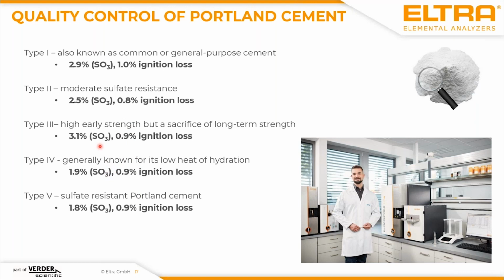the long-term strength of the cement decreases, which means low SO3 content usually means highly resistant Portland cement. Type 5 has only 1.8% of sulfur trioxide, while the moderately resistant has 2.5, and the one which is less resistant, type 3, has 3.1% of SO3, meaning that this has an effect on the long-term stability of the cement itself. So it is important to make sure in the final product that the SO3 content is controlled and meets the specification of what cement producers sell to their customers.